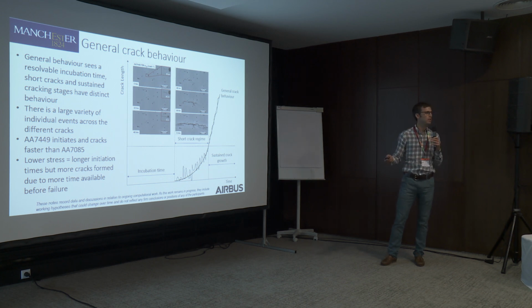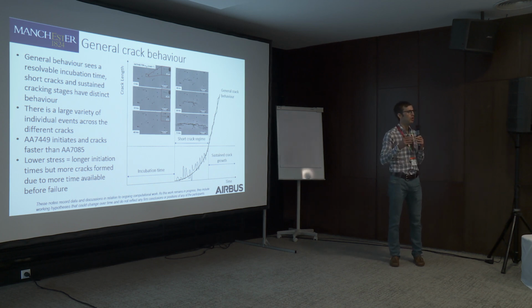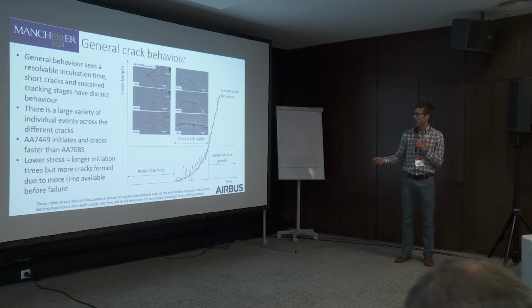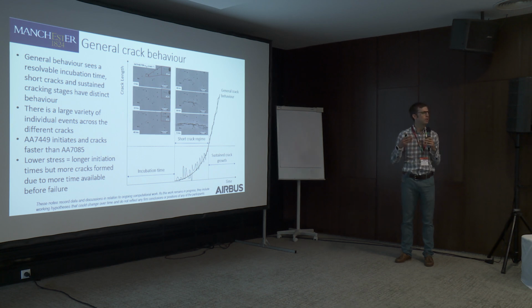But in summary, for all of these systems, we have an incubation time, a time when we don't really observe anything happening, but something is happening because it's reacting to the environment that it's in. And then we have a short crack regime, which is characterised by quite slow and erratic behaviour. And then we have a period where it reaches a much more consistent, higher velocity of cracking.